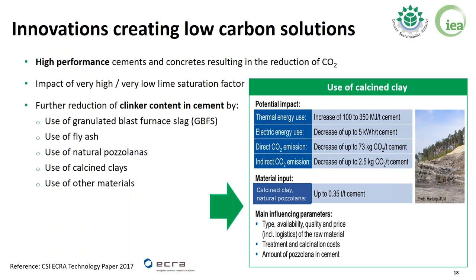As said, due to the drying process and thermal treatment of raw clay, there is an increase in use of thermal energy, but at the same time, there is a reduction of electric energy usage linked with the grindability of the material. Overall, the impact on direct and indirect CO2 emission is positive, as it is quantified, as you can see, in 73 kilograms of CO2 per ton of cement decrease and 2.5 kilograms of CO2 in terms of indirect CO2 emission.